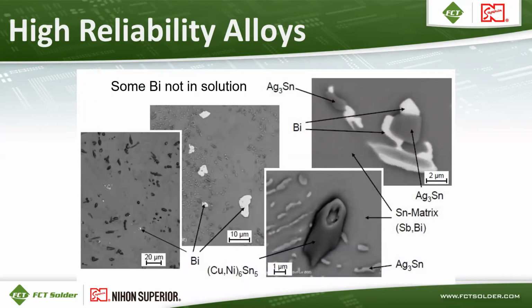But if you add bismuth to a tin matrix, there is a solubility limit. So when you exceed the solubility limit, bismuth will precipitate out as little particles like what's shown here, the lighter gray crystals on the left side of this diagram. You can see that's pure bismuth. And then on the right side of the diagram, you've got Ag3Sn particles and Cu6Sn5 particles with bismuth precipitated around them. So particles tend to create seed sites for other particles to grow. That's what's happening with bismuth when it's exceeding the solubility limit of it within the tin matrix.